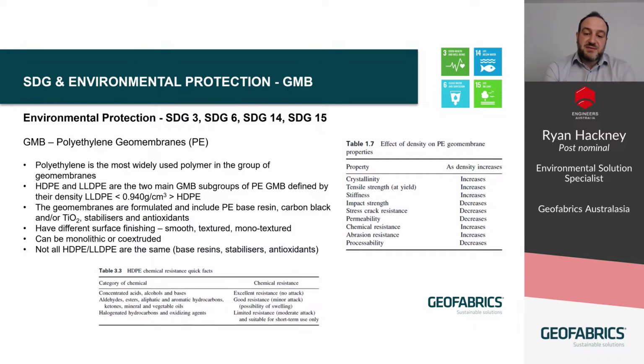There are effects of density on the polyethylene properties. For example, as the density increases, the crystallinity increases. That means we get an increase in tensile strength, stiffness, chemical resistance, and abrasion resistance. But with an increase in density and crystallinity, there can also be an impact on stress crack resistance. The more crystalline a material is, the more susceptible it can be to stress cracking, and that can ultimately be how geomembranes fail in situ.